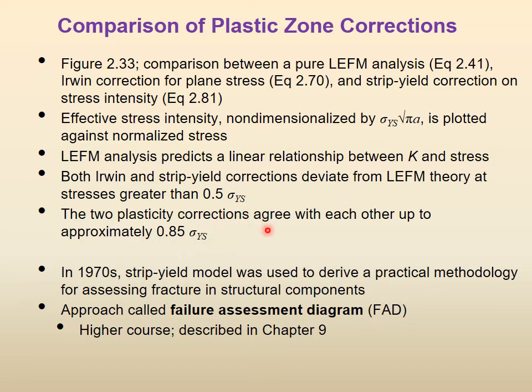So this is a big observation, because as engineers, as science people, we want to know when we need it. If totally linear theory gives you perfectly correct results, then why should you go to a non-linear model and make life difficult? So for 0.25, 0.3, 0.4, 0.45 yield strength, if that is your applied stress, then simply use LEFM and your results are very good.